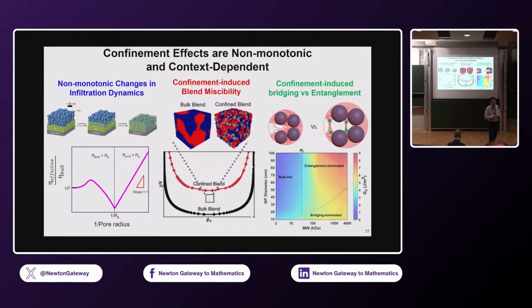Viscosity was non-monotonic with regards to confinement. I think that result was somehow anticipated and is expected. So it's a nice thing. Why would people expect that? In a confined situation, the polymer chains do not have Gaussian statistics. They're swollen. And in your specific situation, there will be logarithmic corrections. So it will increase logarithmically with n, but with a large prefactor, which is a superposition of all the different distances the polymer experiences in your system.